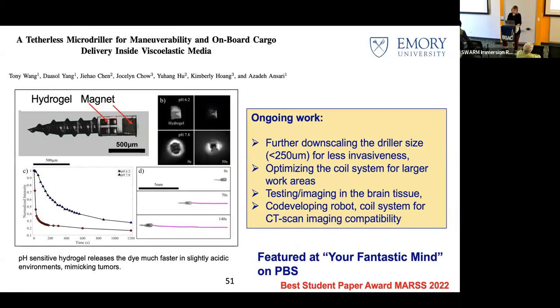And in this case, we just put fluorescent dye. And depending on the pH value of the environment, the hydrogel can swell a lot more, for example, if your material or the environment is more acidic. The reason for this is that tumors tend to have a different pH value than healthy cells. Therefore, if you have a selective hydrogel that releases the drug or the dye at different pH values, this is 6.2 versus 7.8, that's really good for on-demand or local drug delivery.